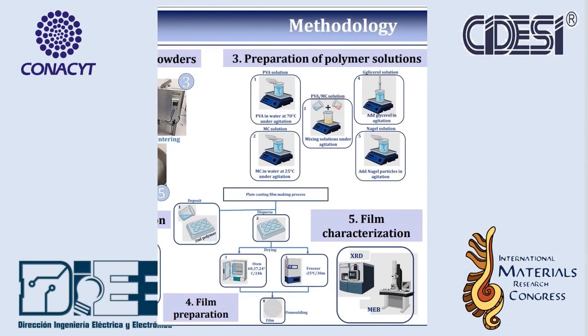For the preparation of the polymer membranes, solutions of PVA, MC, and PVA-MC with and without glycerol and NAGEL particles were fabricated. Subsequently, the membranes were manufactured by the casting method, and the drying and shaping was studied by two methods: convection oven and freeze-thaw cycles drying, where a physical cross-linking is induced to stabilize the matrix and obtain the polymer membrane. The fabricated membranes were characterized by XRD and SEM to determine the dispersion and the presence of the ceramic particles in the polymer matrix.